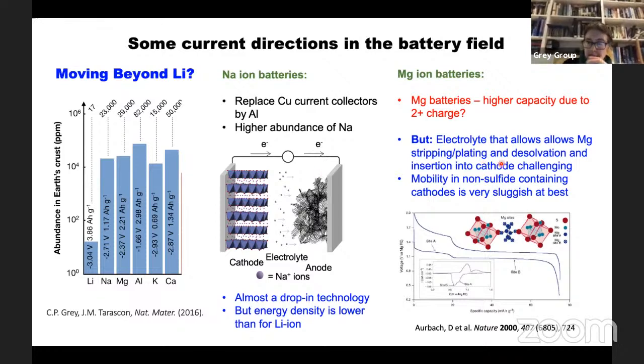But the problem is that magnesium, because it's highly charged, is also extremely well solvated by the ions in solution. So it's very difficult to pull the magnesium out of solution and put it into the material. Or it's very difficult to plate it onto the magnesium surface and do the stripping and plating. And then the next challenge is, how do you move an ion through a solid? And if it's a 2+ ion, the activation barrier of the jump is up.